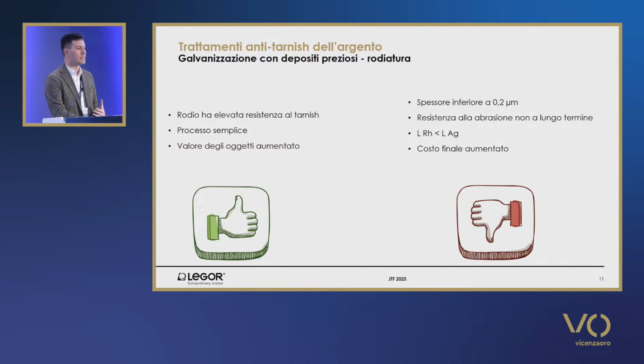substances. Well, rhodium, for example, has a high resistance to tarnish with high chemical inertia, and then it is a precious metal, and so it increases the final value of the object. The problem is that the thickness applied is lower than 0.2 micron, so the resistance is guaranteed, but only for a short period of time, because the thickness will tend to be removed, and the surface of silver will be again subjected to tarnishing.